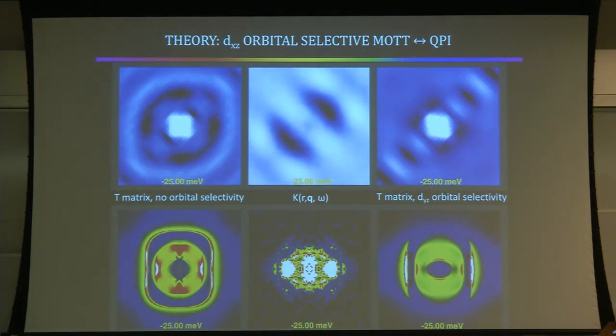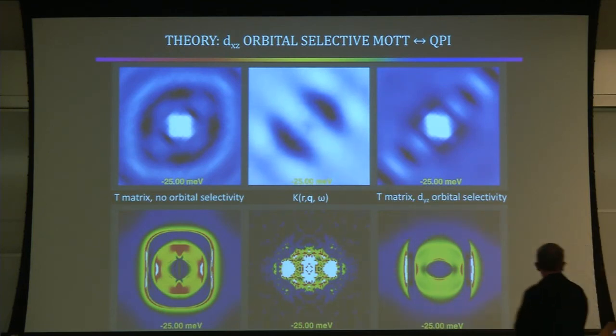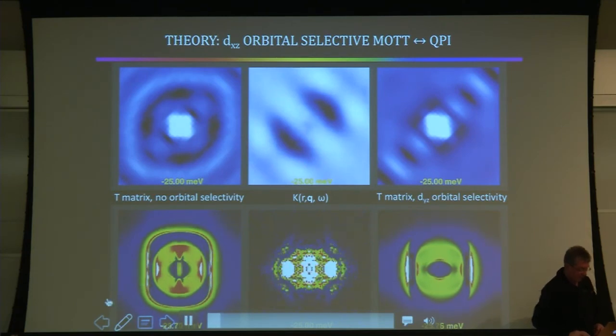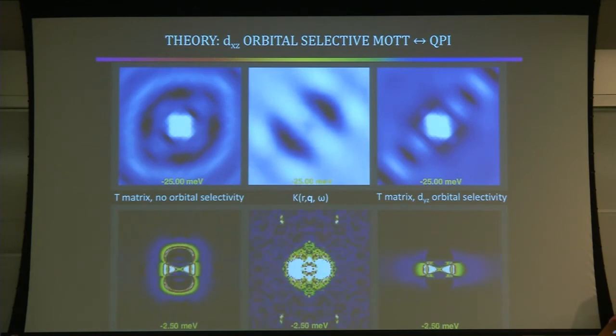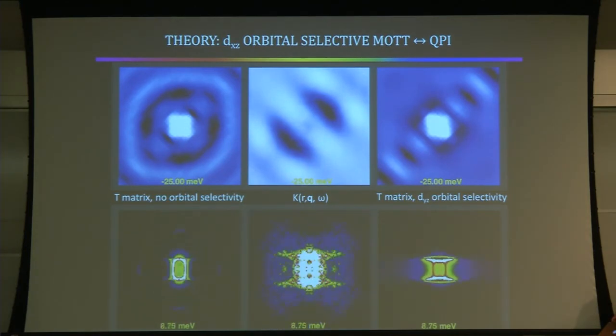Okay, so here's the bottom line. Here's the prediction of a fully coherent 3-band model of iron selenide. Here's the prediction for an orbital selective Mott phase. Here's the data. I can run these movies and you can form your own opinion about whether this one matches this or that in a more appropriate way.